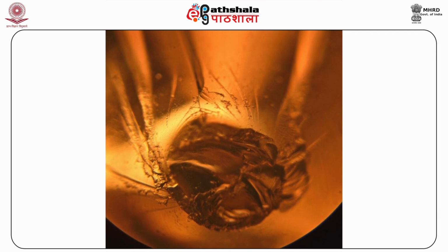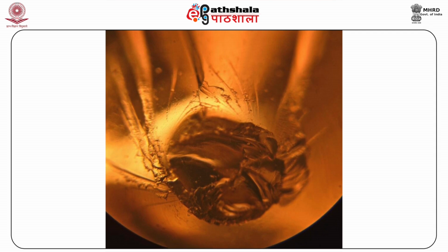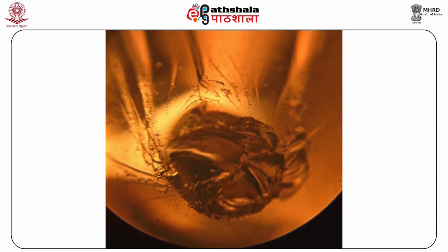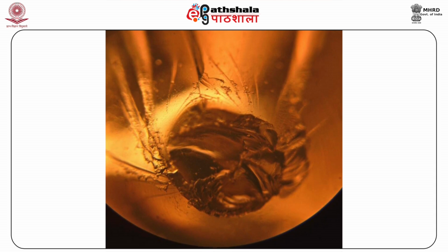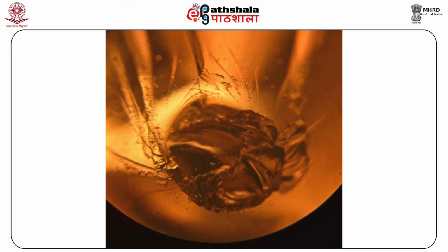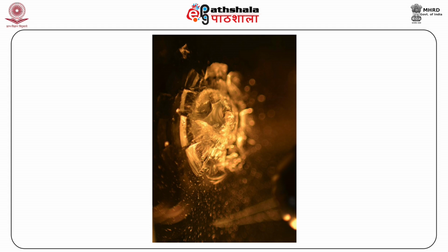However, because of the small size of the shattered fragments at the impact site, the reconstruction of a sufficient portion of the object to display coning effects may not be possible. The size of the hole and the diameter of the crater cannot be used to reliably predict the size of the projectile.